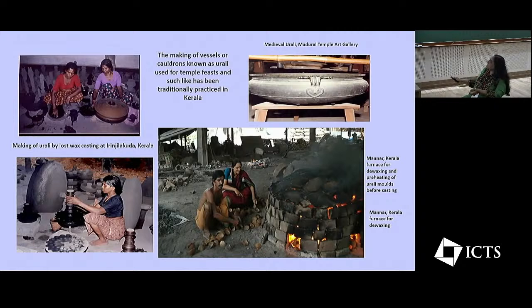The wax model is also built up by using hand lathes. So you see this axle here, and the mold is on that, and then it's all turned on a hand lathe and made really smooth, so you get that very smooth finish. And here, of course, it's quite interesting that the final grade of wax is terribly important for a good finish. And here, they were also using materials like, of course, cow dung and lamp black.